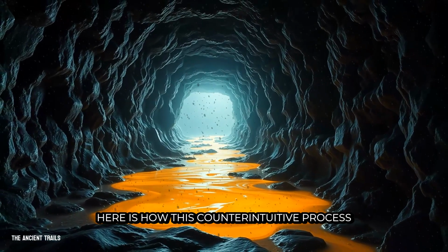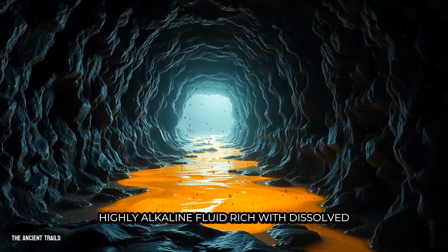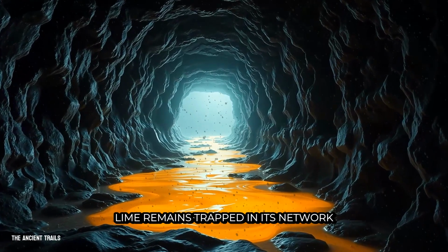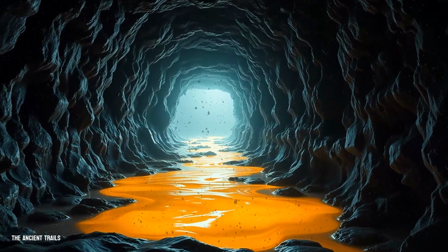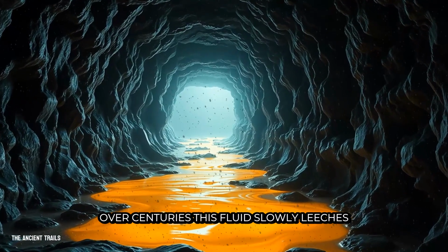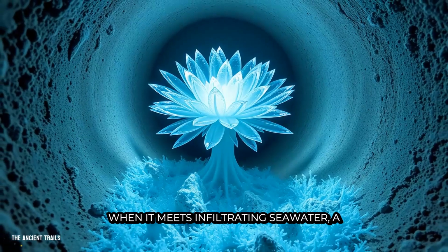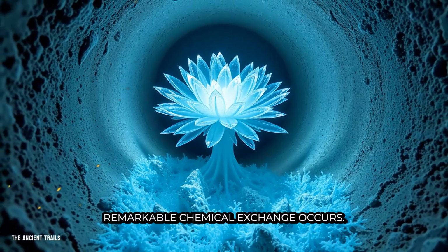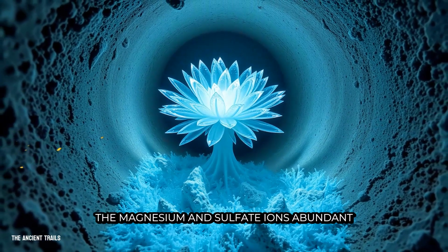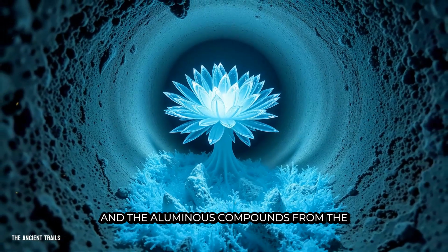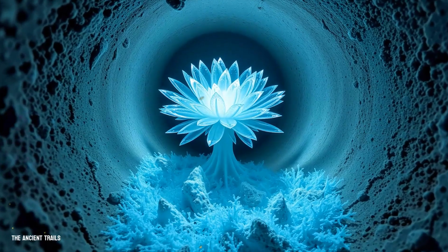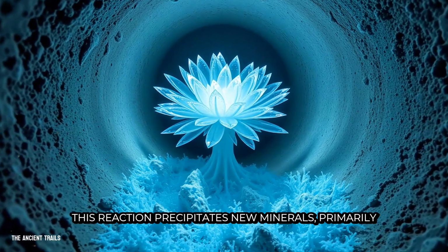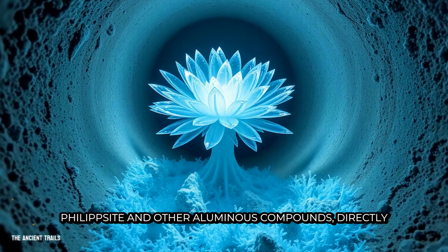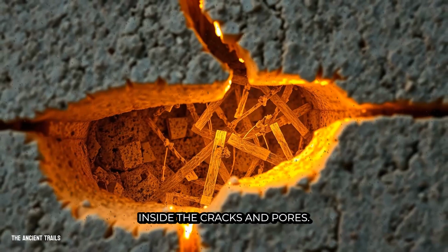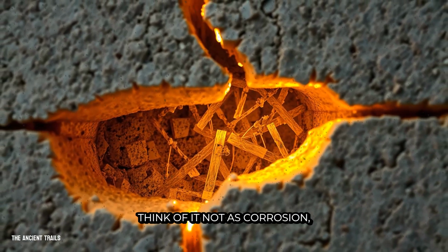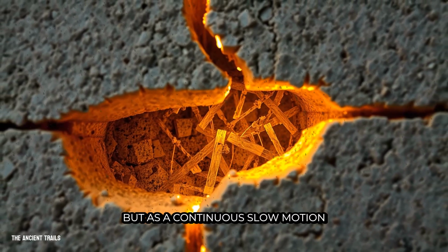Here is how this counterintuitive process works. As the concrete cures, a highly alkaline fluid, rich with dissolved lime, remains trapped in its network of tiny pores. Over centuries, this fluid slowly leaches out toward the surface. When it meets infiltrating seawater, a remarkable chemical exchange occurs. The magnesium and sulfate ions abundant in seawater react with the lime and the aluminous compounds from the volcanic ash. This reaction precipitates new minerals, primarily more of those plate-like crystals of phillipsite and other aluminous compounds, directly inside the cracks and pores.